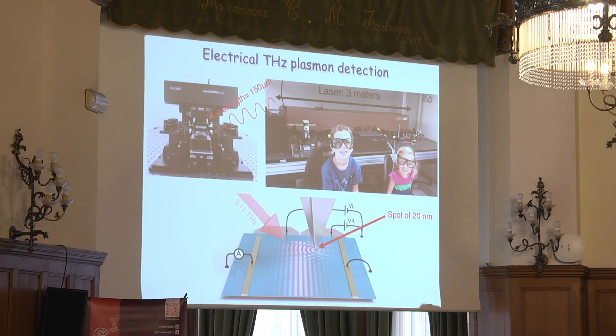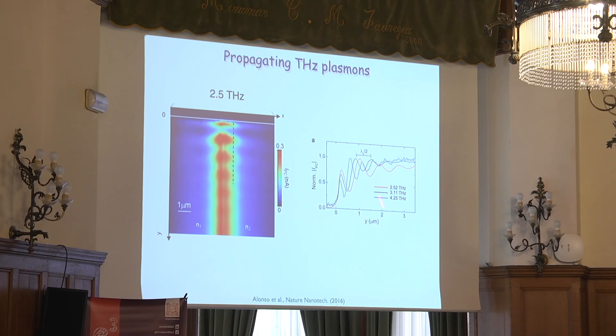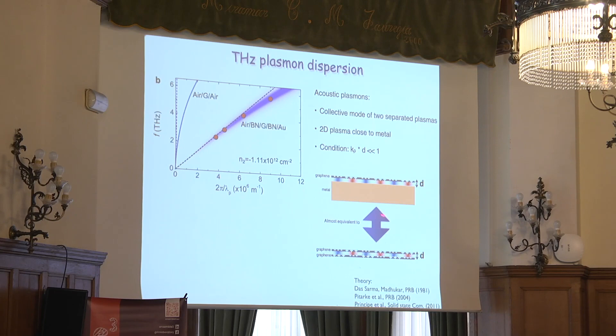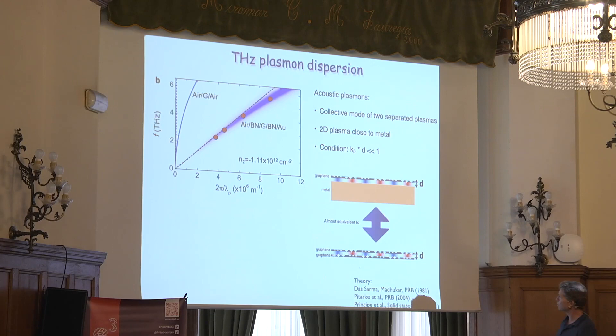For students: when you believe something does not work, or your supervisor says it will not work, you should try it — because there's a good chance it will work. One thing found with terahertz plasmons is that the dispersion is linear. Pablo explained how plasmons in graphene are square-root-of-k, but here it's linear — because a gate is close by and the wavelength is much larger, giving screening of plasmons by the metal. You can see this as an image, as a mirror image, with two layers of graphene with opposite excitation polarity. This is called a screened plasmon, leading to a linear plasmon dispersion, also called an acoustic plasmon.